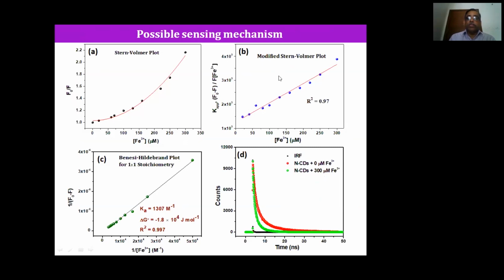We'll slowly look at this. We made a thorough analysis of the fluorescence lifetime quenching, Stern-Volmer analysis, and also the ratios of binding, the stoichiometry of the metal ion to the fluorophore. You have done the Benesi-Hildebrand analysis, and it shows a stoichiometric ratio of 1:1.